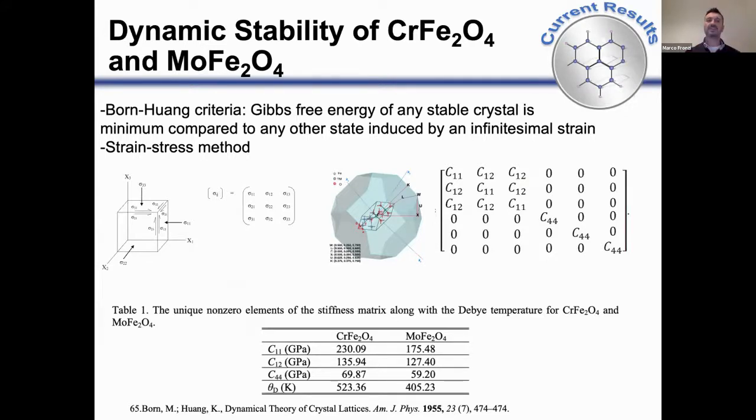So we use the strain-stress method to calculate the elastic constants and see if there's any discrepancy. Any negative value would imply an instability of the compound.